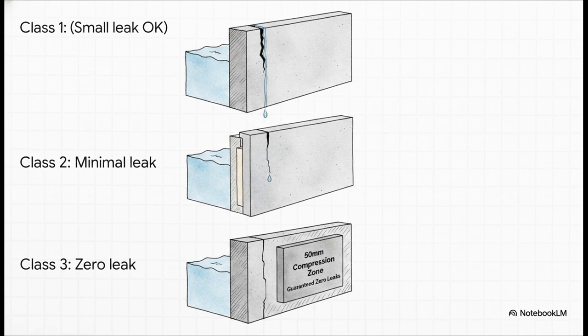Class 1, where maybe a small leak or a little surface stain is okay, holds steady at that 0.2 millimeter limit. Then you have Class 2, where appearance really matters and we only want minimal leaks. That requires 0.2 millimeters with a liner, or it drops down to a stricter 0.1 millimeter limit. And then there's Class 3. This is where absolutely zero leakage is tolerated. Class 3 demands a 0.1 millimeter crack limit, and it has to come with a guaranteed 50 millimeter compression zone inside the concrete section itself.